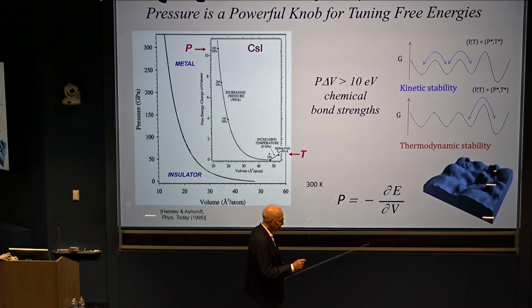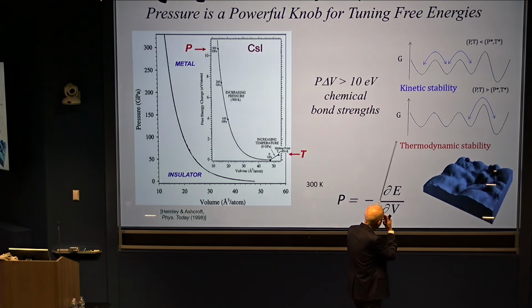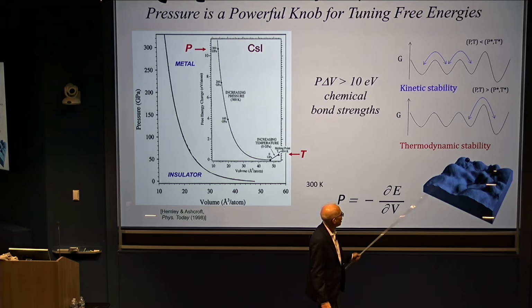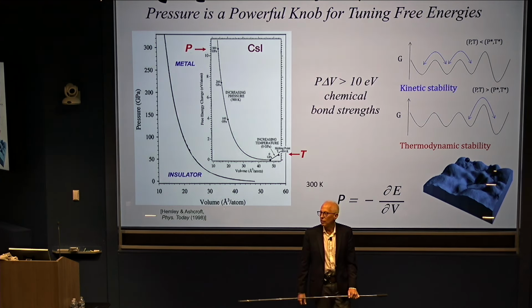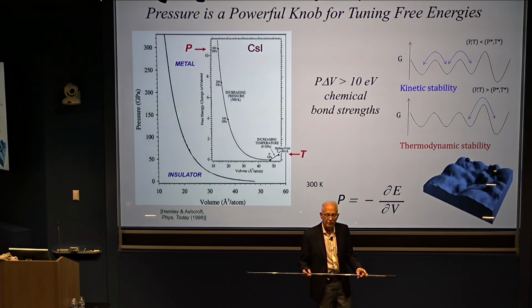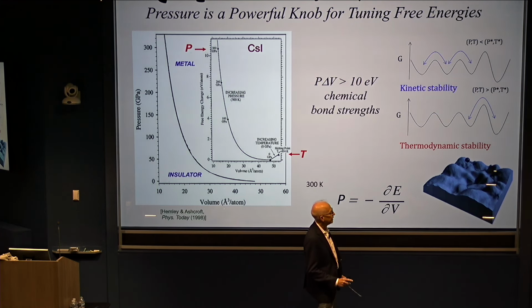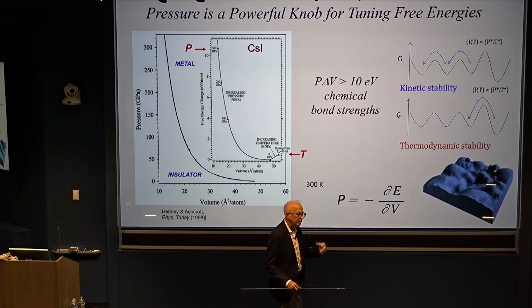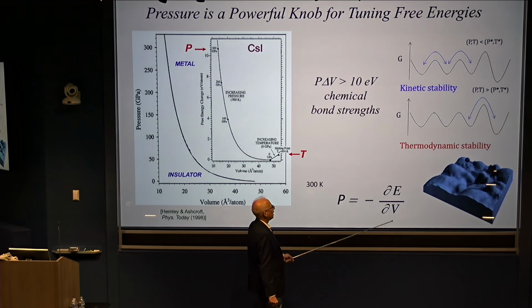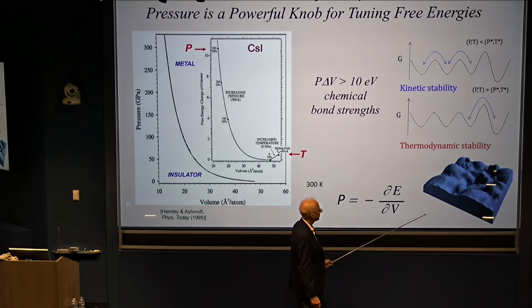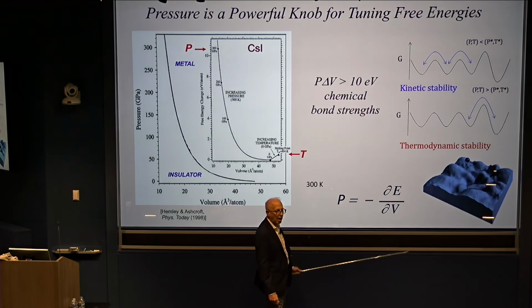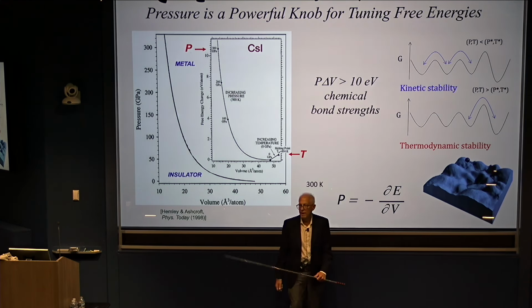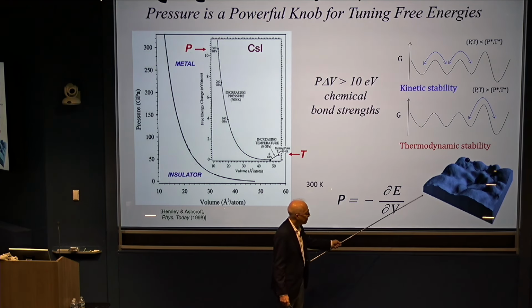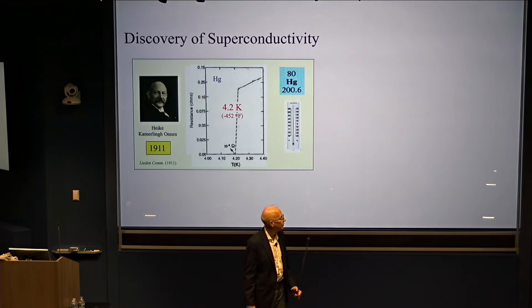What this also means is we have to think about two kinds of stability. We have thermodynamic stability that's sort of implied by this. We're looking for the ground state of a material at very high pressure. But we also have the possibility of metastable states, so kinetic stability, that could be very important. And after all, there are a lot of interesting materials that are kinetically stable. Diamond, for example, is kinetically stable. It's not thermodynamically stable under ambient conditions. And it's very useful, of course, as a stone, as an object, as a consumer gem, but it's extremely important for many kinds of advanced technology. So what this means is that pressure is a knob for tuning across energy landscapes. I'll come back to this several times, looking for minima, both the metastable minima and global minima on the system.